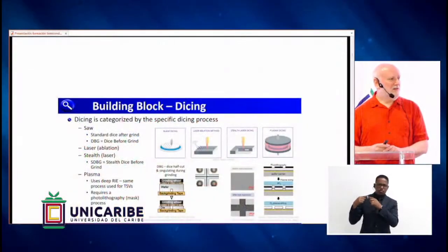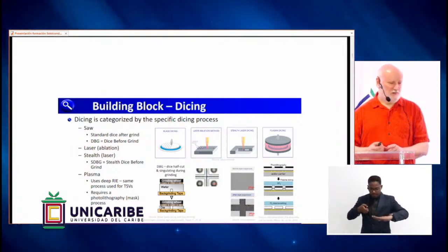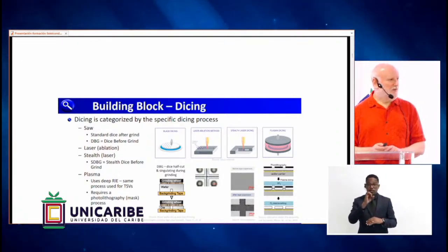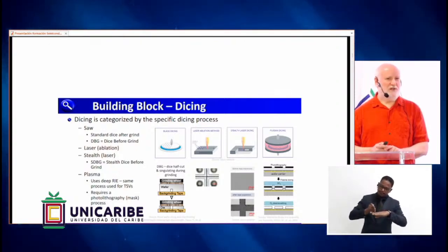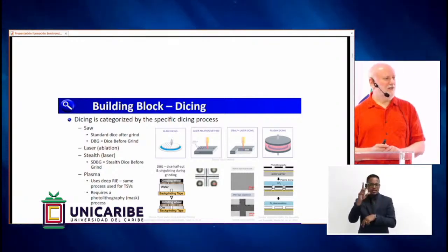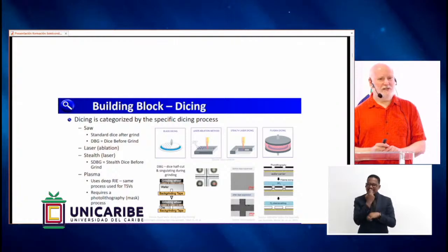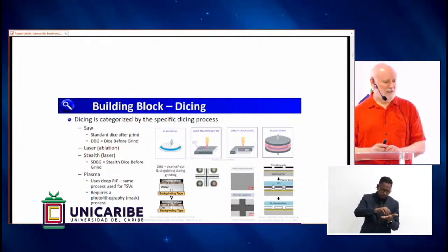And there are a number of different ways to dice. The traditional method, which has been used for a long time, is a saw process. And that's literally a saw. It looks like a circular saw, specialized with abrasive material on it that cuts through the silicon or whatever the wafer material is. But there are other ways too. Sometimes lasers are used. There's something called stealth laser, where the laser is focused on the interior of the crystal structure of the wafer and actually dislodges the crystal structure so that it can be easily broken and separated. And then there's plasma dicing. If you're not familiar with plasma, it's a highly ionized gas. And it is good for etching. It's a typical etching process used in semiconductor fab, but we sometimes use it also in packaging and assembly, especially here in the dicing operation.